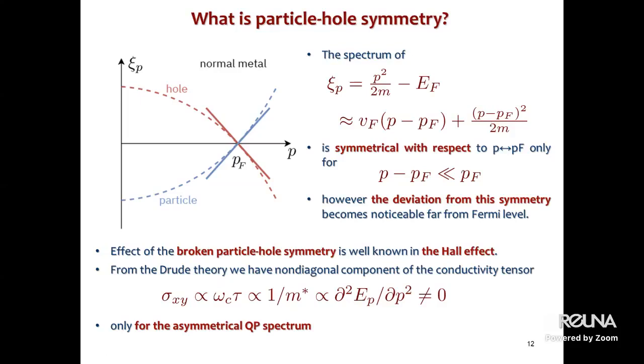However, it's becoming non-negligible if we're moving away from the Fermi level. So, the effect of broken particle-hole symmetry is well known in the theory of the Hall effect. From the Drude theory, we have a non-diagonal component of the conductivity tensor only for an asymmetrical quasi-particle spectrum. Indeed, if we have a symmetrical one, we have non-diagonal terms zero. If we have asymmetry, this term will become non-zero, and then we have a Hall effect, and consequently, we have an inverse Faraday effect.